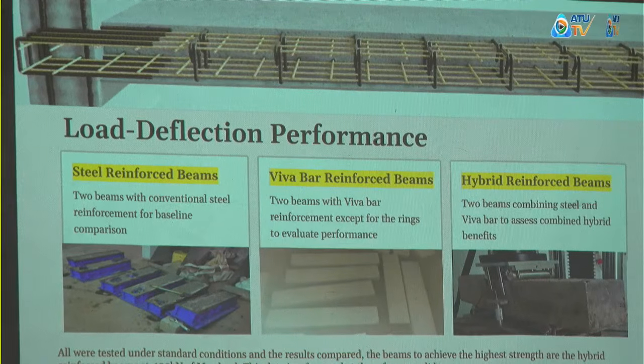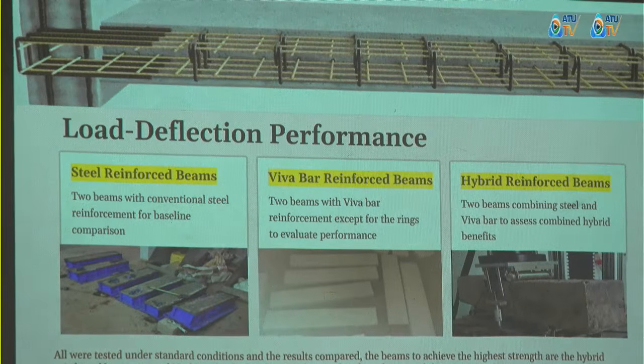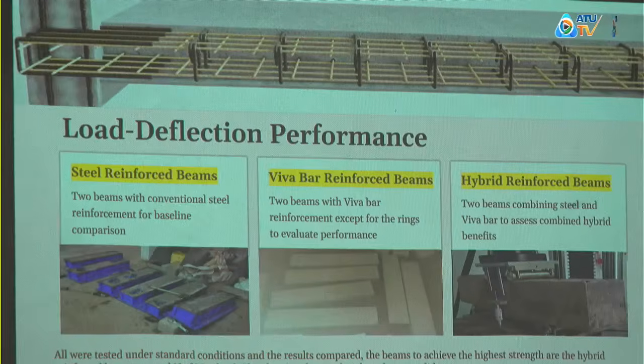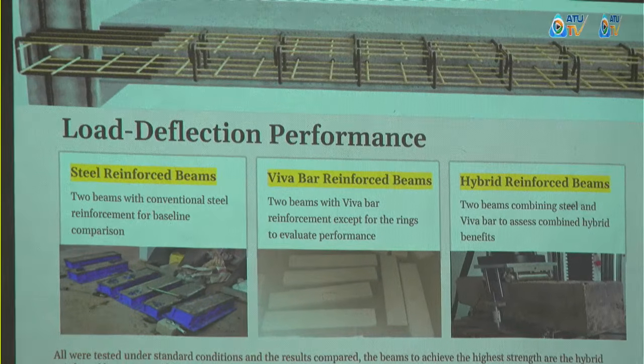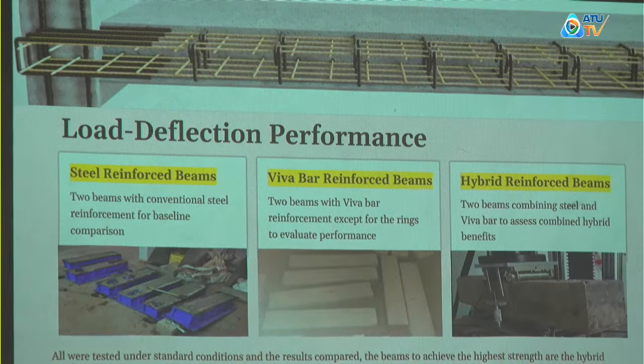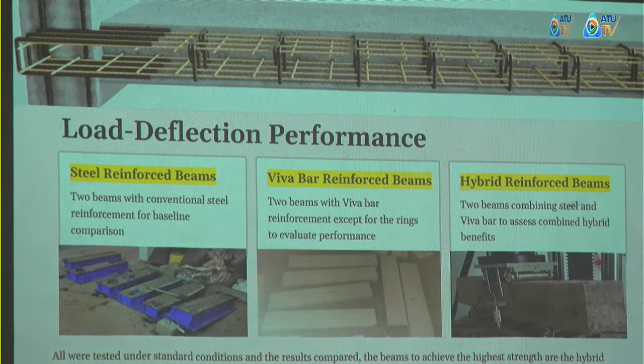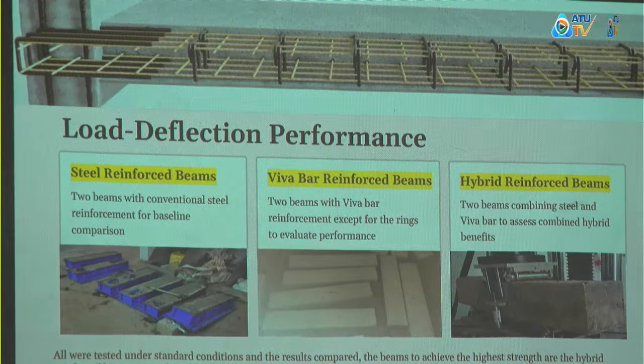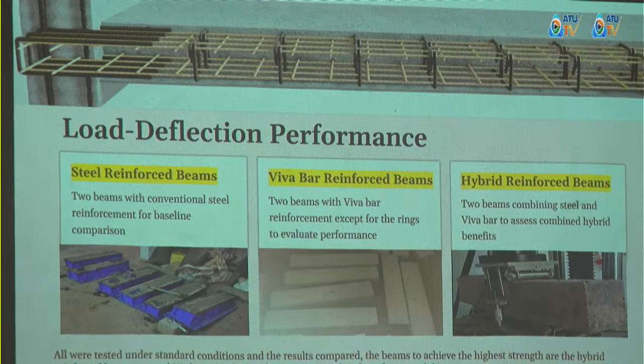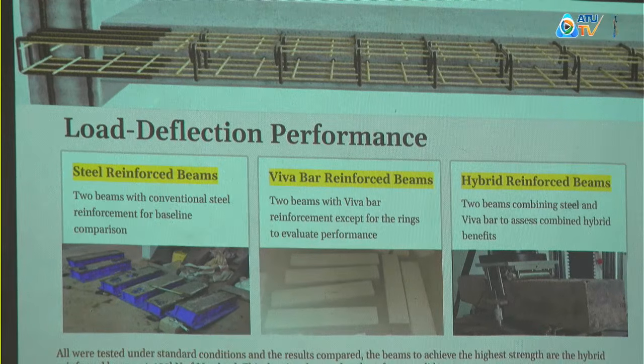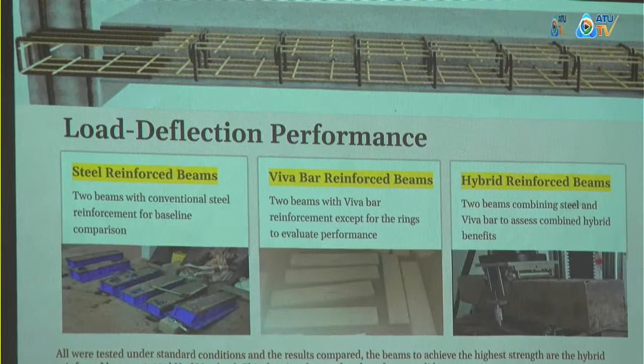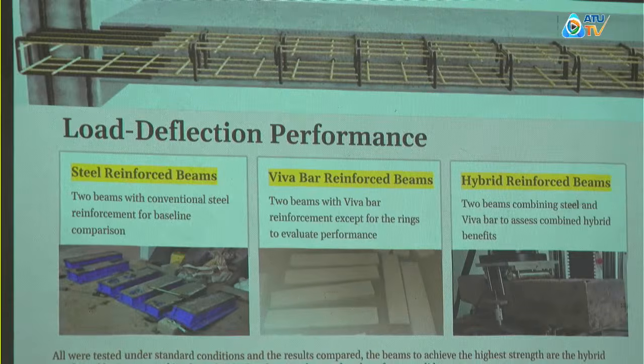The beam that achieved the highest strength when I took the sum was the hybrid beam, because this ensures that the materials complement each other. Steel contributes to the compression and the shear at the end, which fiberglass is not able to do as effectively. On the other hand, the fiberglass does tensile strength better than steel and holds a much higher strength when it comes to tensile.